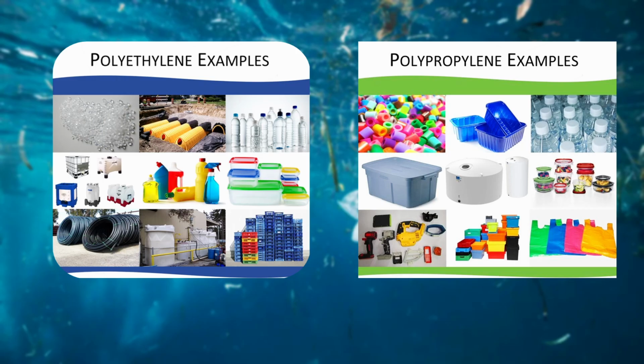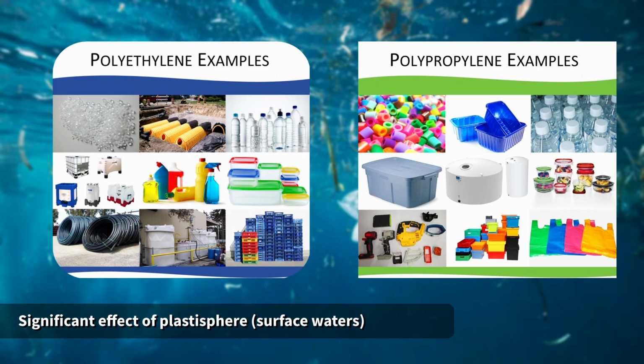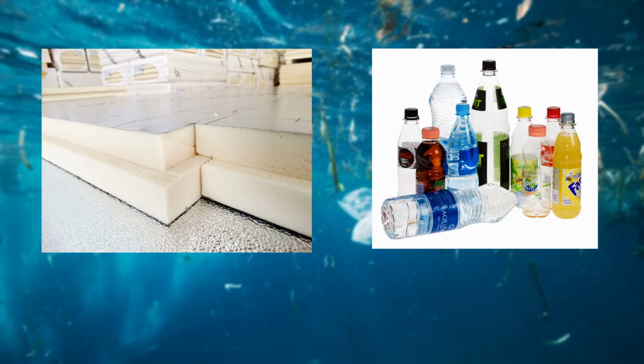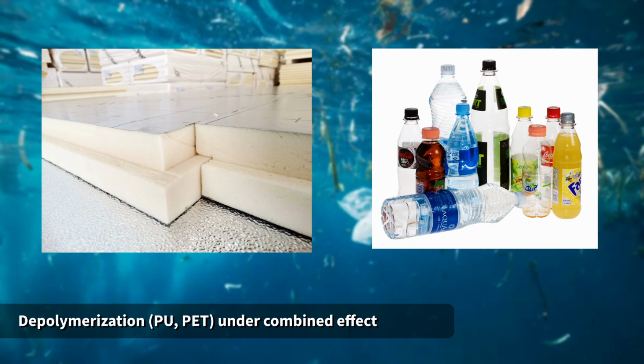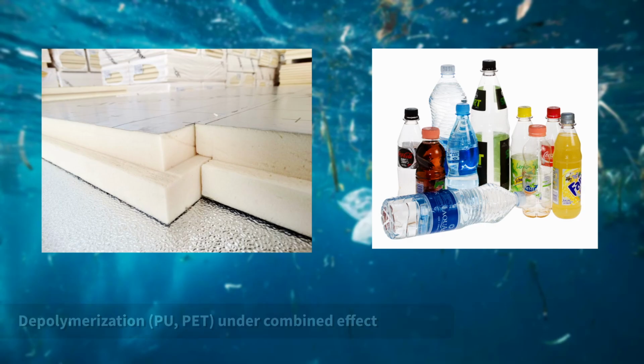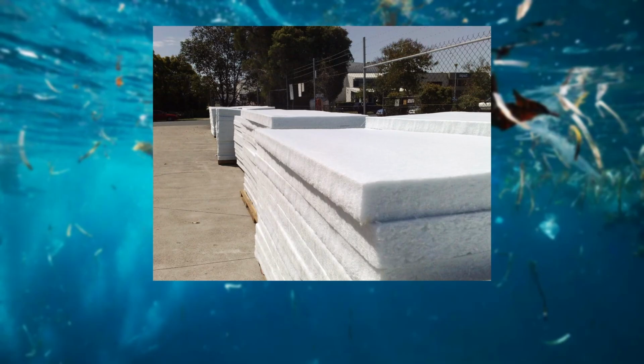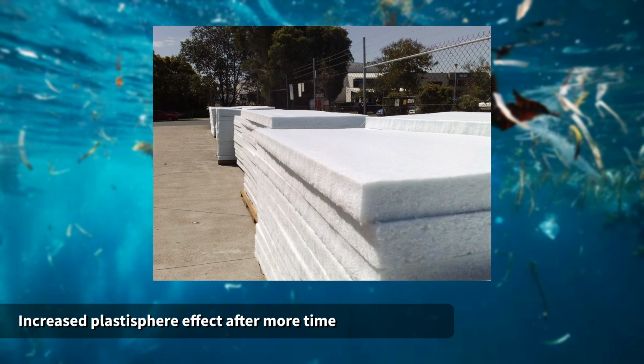Polyethylene and polypropylene degrade significantly faster in plastisphere conditions, especially in warm, oxygen-rich surface waters. Polyurethane and PET undergo partial depolymerization, often requiring cooperation between fungi and bacteria. Polystyrene shows the most resistance, but surface erosion and oxidative pitting increase after 180 days or more of biofilm colonization.